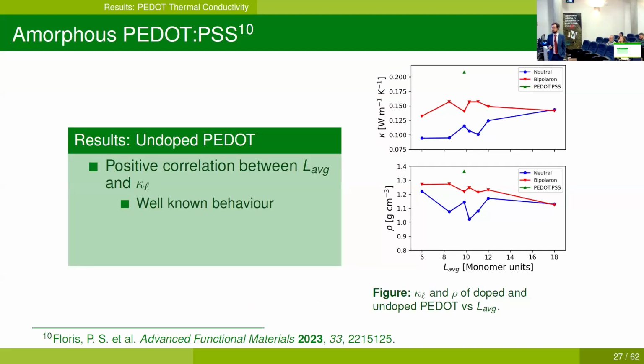Moving to the results. So let's look at undoped PEDOT first, which means the blue lines. What we see is a positive correlation between kappa L and the average chain length. This is a very well-known behavior in polymers in general, which we expect to see since when we increase the average chain length, we increase the covalent bonds within the chain, and this favors intra-chain transport, and this results in an overall increased thermal transport. When we look at the density in the samples, there is no clear trend, but there is some sort of a weak negative correlation between density and average chain length.